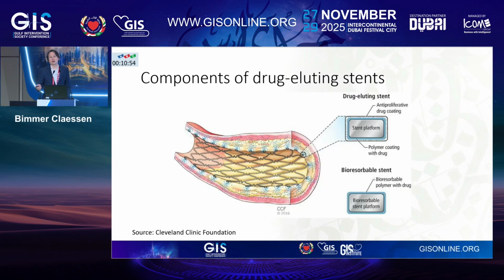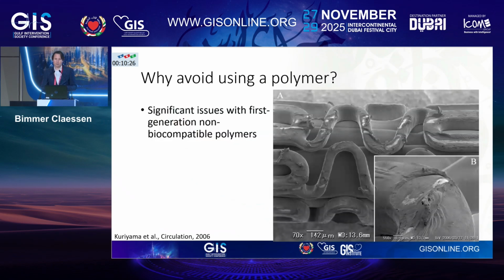So you're probably well aware of the components of drug-eluting stents. There's a stent platform, it's metallic, it's either stainless steel or it's a chromium-based alloy. The chromium-based alloys usually allow for smaller strut thickness. Then there's a coating with a drug. It can be paclitaxel or sirolimus analogs. Paclitaxel has gotten out of fashion, so it's basically just sirolimus right now. And then there's some way to elute the drug over a prolonged period of time, and that traditionally was a polymer. But why would we maybe want to avoid using a polymer?